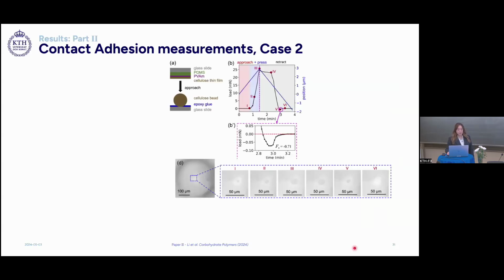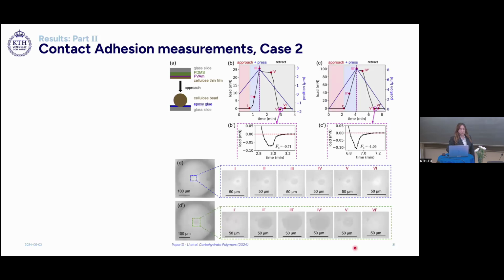Looking at case 2, where we have a cellulose bead measured against a cellulose film spin-coated on PDMS, we can see that there's no attraction on approach. However, we have a separation force. And this separation force increases when we increase the load from 25 millinewtons to 100 millinewtons. And this increase is related to the increase in contact area, which we can see in the optical images.